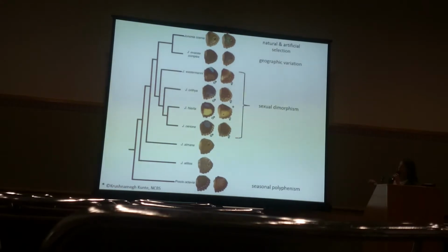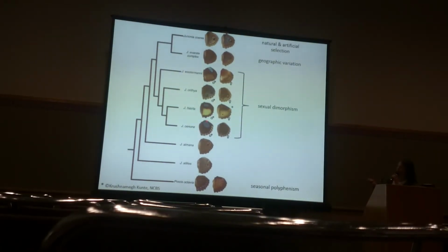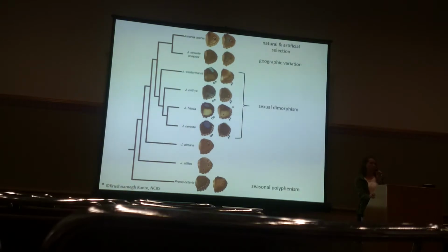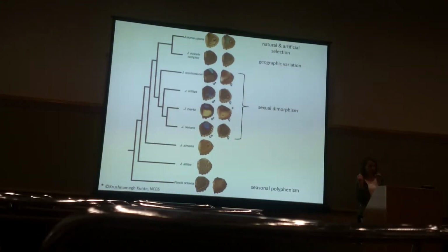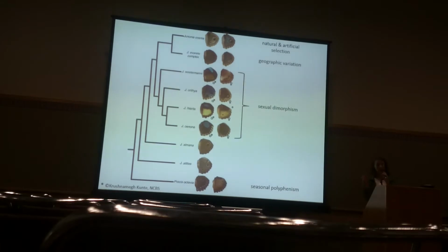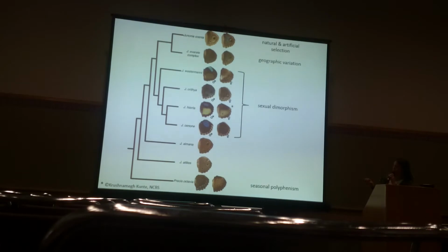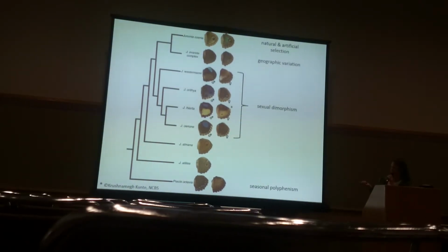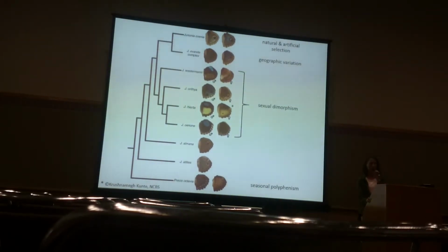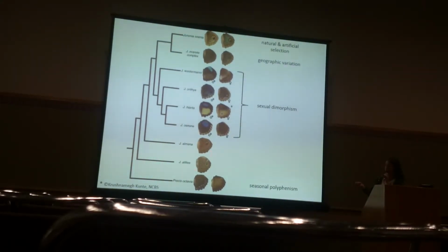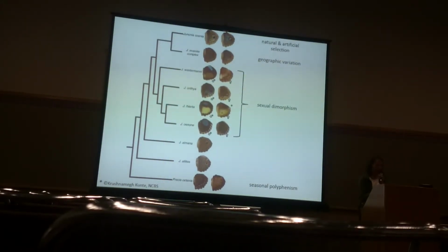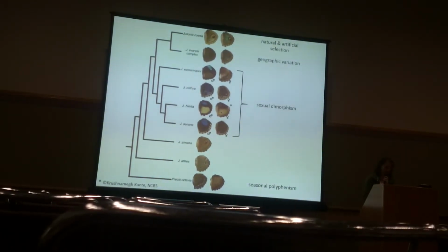But what might surprise you is that even some of these other colors, like oranges and yellows, that you would think could easily be produced by a pigment, they color match. So they'll have a yellow or orange pigment, but they'll also have a yellow or orange thin film as well, reinforcing that. And then, for example, these two species, they're just kind of buff and beige. You would not think of them as structurally colored. They do have a little bit of a pigmentation difference, but actually, I think more important is the difference in the thickness in their laminas as well. So yes, this seems like this is an important and common tool that they use in their coloration kit.